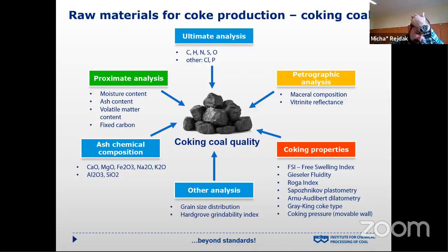Gray-King coke type is the test which can determine the coking properties. It's a simple coking test. Crushed coal is heated in a glass retort, and then the shape, texture, and appearance of the obtained coke is compared to the standards to give a letter, which is the Gray-King coke type. Of course, the letter values go from A, which means non-coking coals, to G, and after G we have G1 to G9, which indicate superior coking properties.